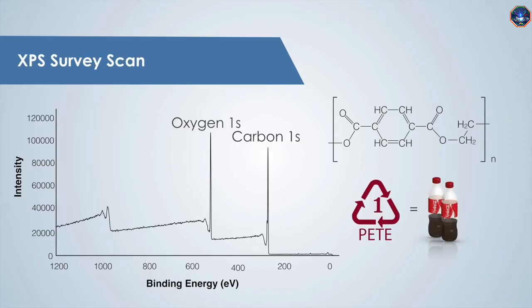Polyethylene terephthalate, or PET, is a polymer often used to make beverage bottles. The peaks in this spectrum correspond to the positions for carbon and oxygen in the PET, consistent with its chemical structure. XPS can also tell us how much carbon and oxygen are present by comparing the areas under each peak.